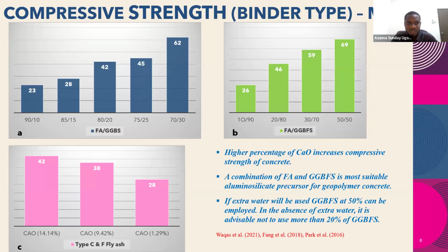So if you look at it, you see that most times, if you use only fly ash, because the calcium oxide in fly ash is very low, you're not likely to get a very high strength. At the same time, you can get a very high strength with GGBS if you use slag, because it has a high percentage of calcium oxide. But